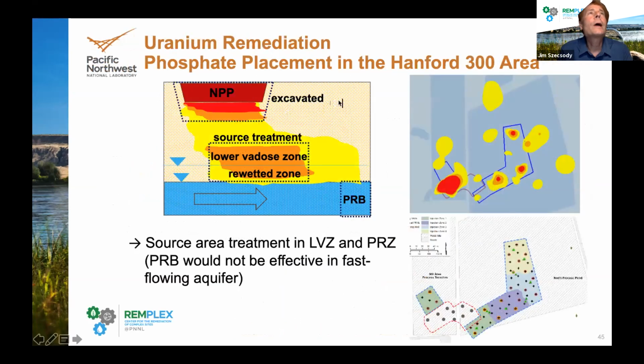Given that understanding, in the Hanford 300 area, this diagram shows where treatment was actually done in the field. Again, North Process Pond with high uranium concentration. This part was excavated, and uranium was left in either the periodically rewetted zone or the lower vadose zone. The 57 wells that I'm showing here had a screened interval here and also here. So basically, CHPRC did source area treatment, and we did not do a PRB treatment down gradient from the system. Shown on the right side, this outline is the North Process Pond, and these bright colors are uranium concentrations. These areas and the dots here are where the wells were drilled and the phosphate was injected. So that's where we did the placement.